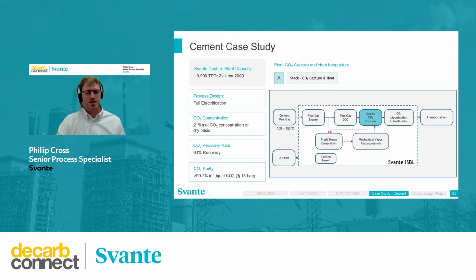Since our system is not pulling steam from outside the battery limit, we wanted to show the heat integration within our site. So the red dotted lines show the use of low-grade heat that runs our MVR system. So this is a vacuum flash system. We're able to pull steam. We're then able to increase the heat of that steam through mechanical vapor recompression. For this site, and for many of our technologies, we're able to be fully electrified and fully independent of the plant for steam use.